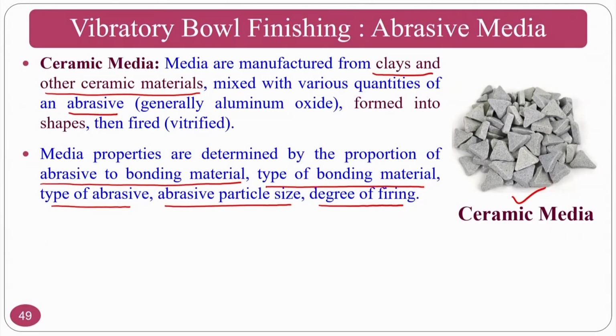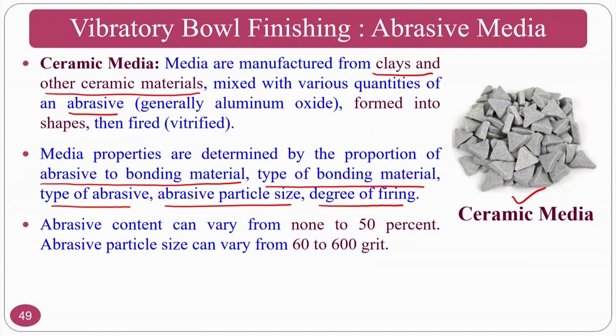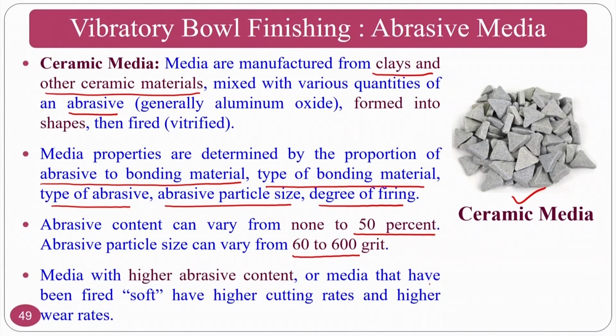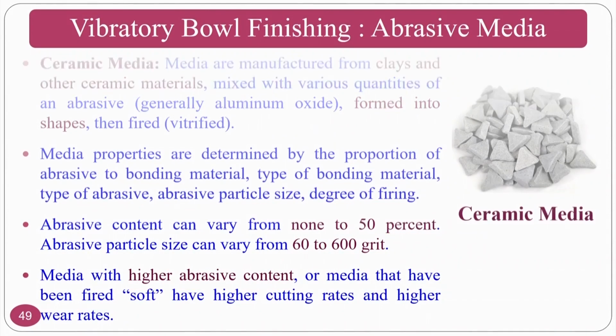At the same time, the degree of firing: if the firing of these particles during manufacture of these triangular beads is very high, the strength of these particles will vary, and accordingly the material removal also will vary. The abrasive content can vary, and abrasive particles can vary from 60 to 600 grit size, that means abrasive particle size. Media with higher abrasive content, or media fired less, will have higher cutting rates and wear rates will be very high.